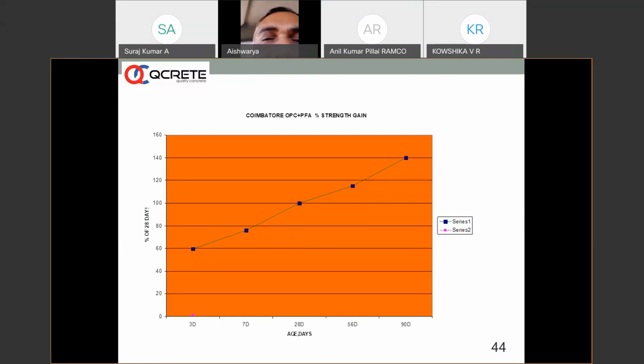Again, this is a graph which represents an average of about 800 results. Each result is an average of 3 cubes, and we can see from here the OPC plus fly ash mixes. The fly ashes from Ennore thermal power plant, Mettur thermal power plant, and Tuticorin thermal power plant were used actually. And you can see here there is a 40% jump from 28 days to 90 days.